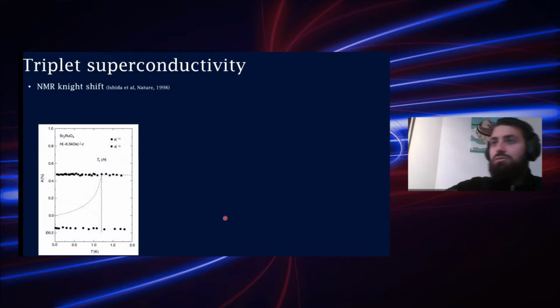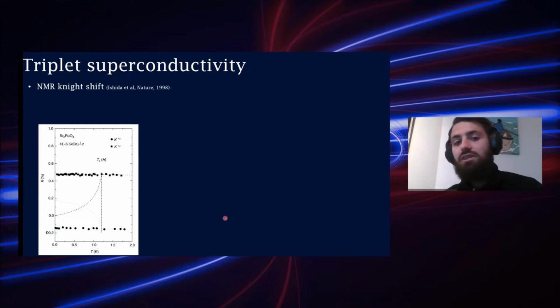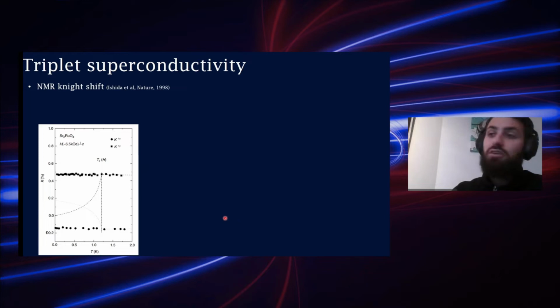Quite early on, it was found by NMR Knight shift that the spin susceptibility is not suppressed in the superconducting state, indicating that there is a spin component to the system.